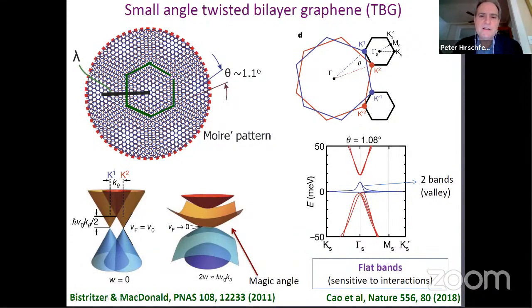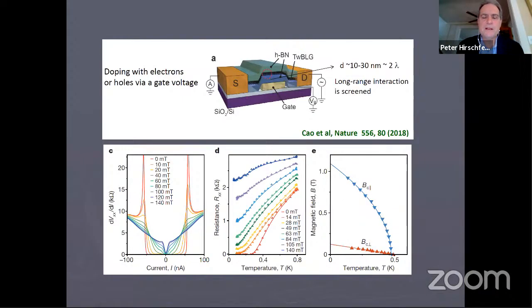And the idea is, why should twisted bilayer graphene be a good unconventional superconductor? Because carbon is not known for having a lot of d electrons, which are going to cause electronic correlations. But the point here is that what's important is the ratio of the bandwidth of the material to the correlation strength. And the bandwidth here is extremely narrow. And so that might mean that this is in a regime where you can see the same kinds of correlations as you see in cuprates.